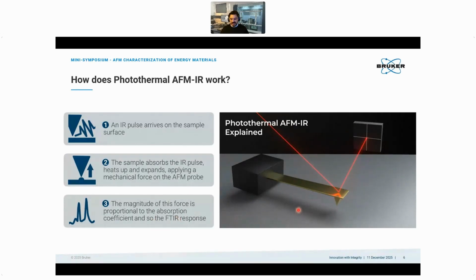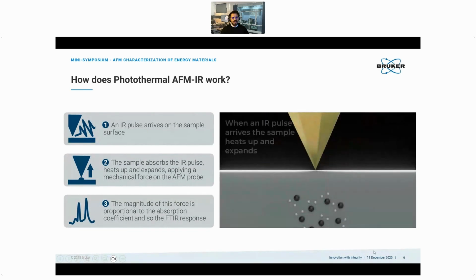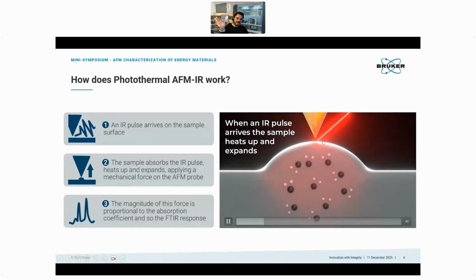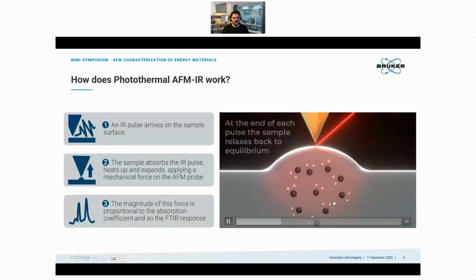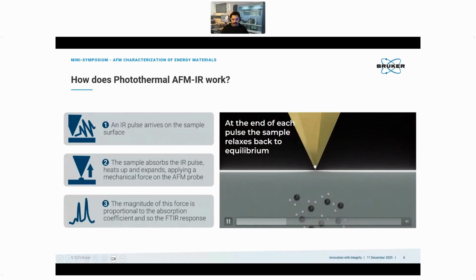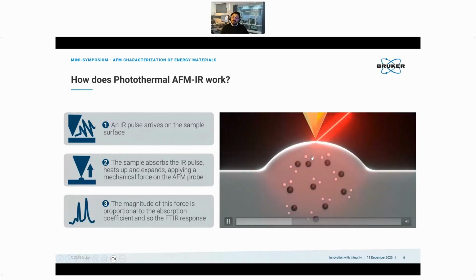I would like to use this animation here because it helps me a lot to visualize how things are happening. This is a cantilever touching the surface, and this laser here is the optical lever to measure its deflection. When we send an infrared laser to the sample, if the wavenumber of that laser can be absorbed by the sample, the sample will expand, pushing the tip upwards. When the tip is pushed upwards, the cantilever will bend, and this is exactly what we measure in AFM. The amount of this expansion will give us different bending.